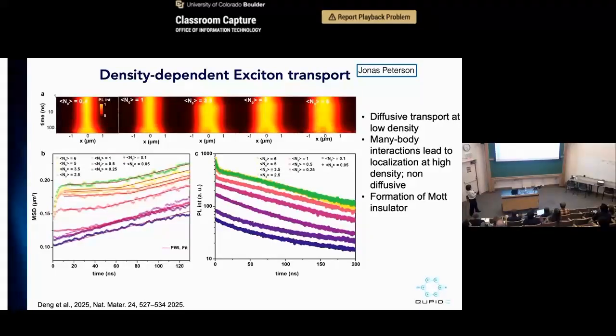At a very low limit, when you very dilutely fill this lattice, say 5%, what you see is this exciton just slowly diffusing around, right? Kind of like what I showed earlier, in the diffusive regime you will have the mean square displacement that is linear with time. So you just see a slow diffusion of this exciton at the low density limit. And as you increase density, something very interesting happens: this mean square displacement starts to have a plateau. It no longer changes with time at early time. So it's totally stopped. The exciton motion stops at high density.